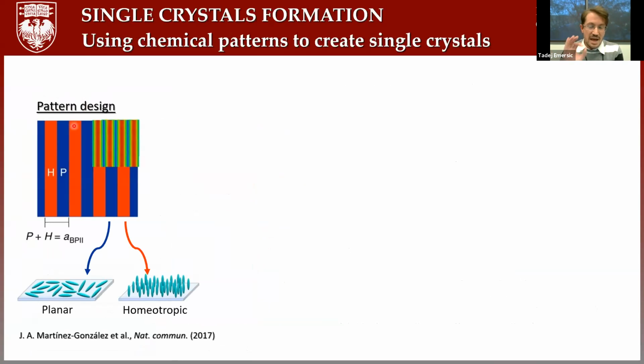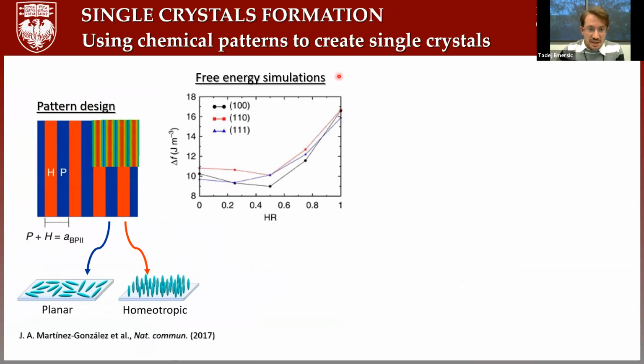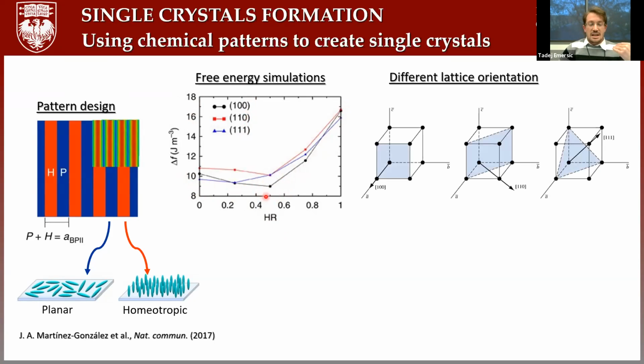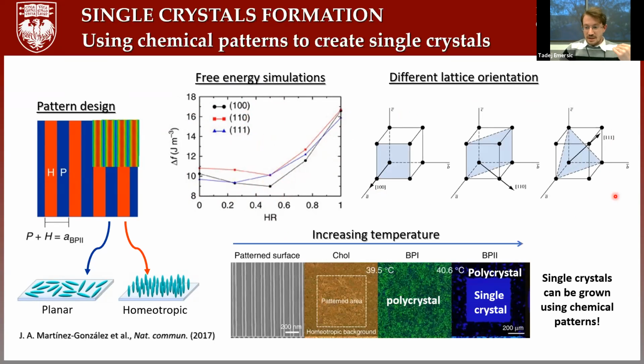So based on the dimensions of the homeotropic and planar regions of the patterning that we are using, we can make theoretical predictions of which blue phase with which lattice orientation is going to form a single crystalline structure. And this is going to be the one that has the minimum of the free energy. Let me mention that different lattice orientation just means how we see the unit cell relative to the surface. And here at our university, our institute, people already showed a couple of years ago that if we have this patterned surface of homeotropic and planar regions, and we place the blue phase on top of it, we really can form single crystals, as we can see here. So how are those experiments going?